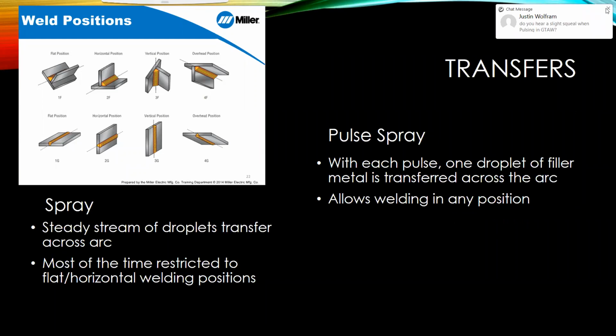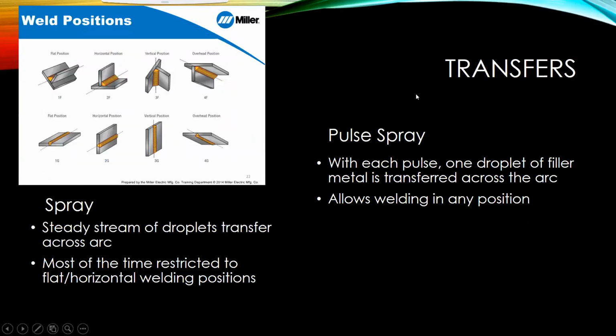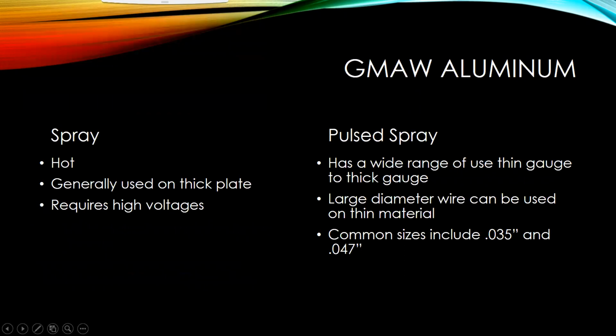When we're talking about pulse spray transfer, basically we're ramping our current, or amperage, up and down, and with each pulse, a droplet is transferred across the arc. This allows welding in any position. A continuation of that: spray transfer is typically very hot. It's generally used on thick plate, and it requires high voltages. Pulse spray has a wide range of use. We can be welding on very thin aluminum, 18 gauge, 20 gauge, and we could be welding up to half-inch thick aluminum. So it has wide usability.